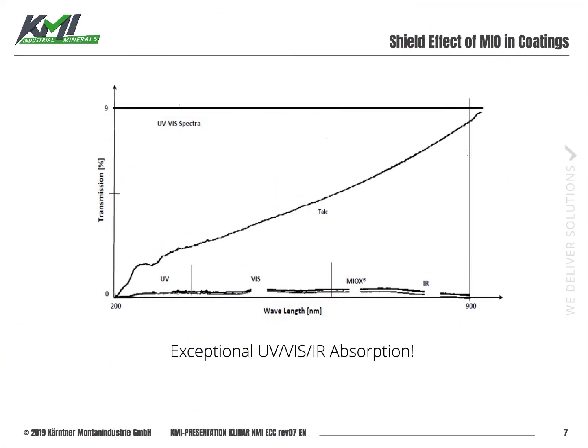The next effect of MIOX is the so-called shield effect. What you can see here is we measured the transmission rate on a polypropylene filled film. We produced a 200 microns thick film. One film was filled with talcum powder just to compare, and the other film was filled with Miox, again at the same pigment volume concentration, and we measured the transmission rate over the whole spectra.